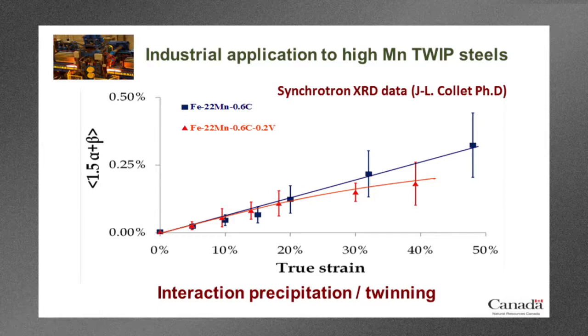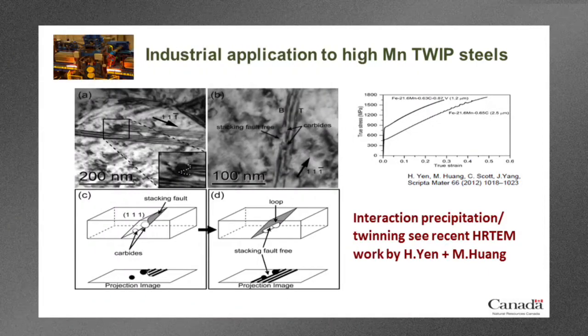So you can see that up to about 20% of strain, there is no real difference in the twinning kinetics, if you like, between the two steels. But after 20% strain, there is a saturation in the precipitation data, which explains the change in the flow curves. What is actually happening is that there is an interaction between stacking faults and very small precipitates, and there is some very nice recent work being done by Yen and Huang.